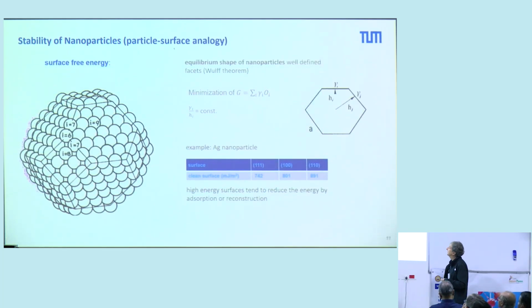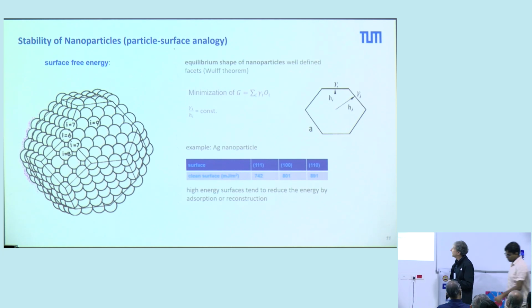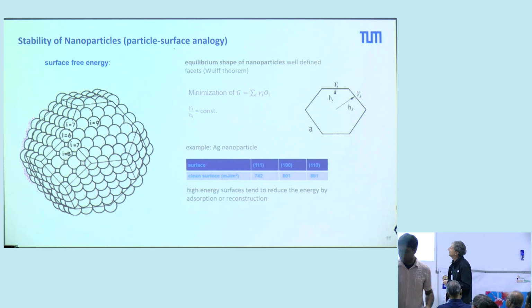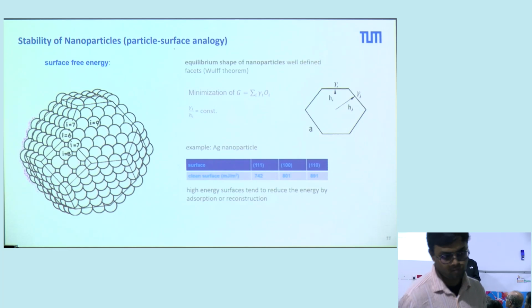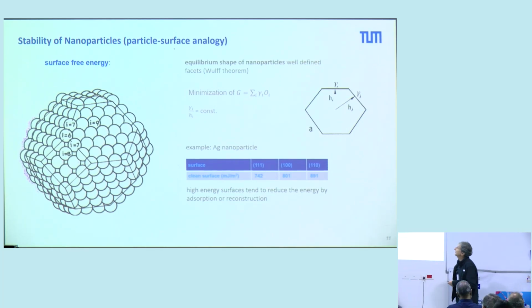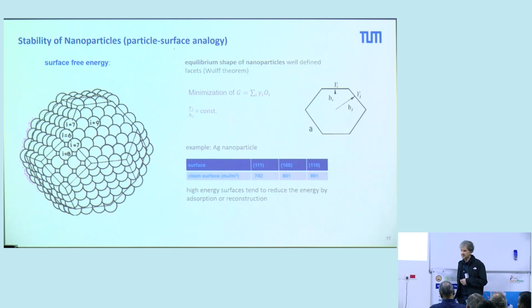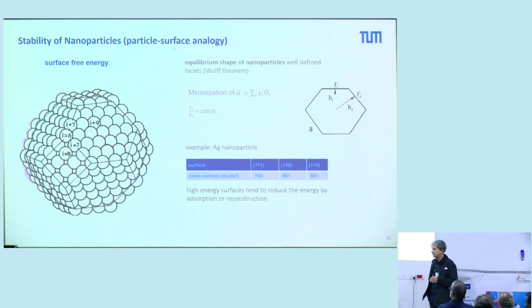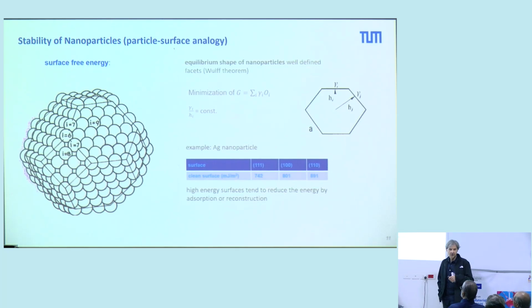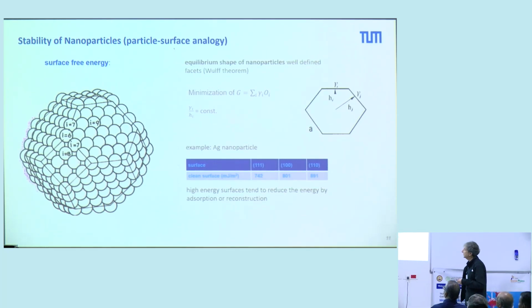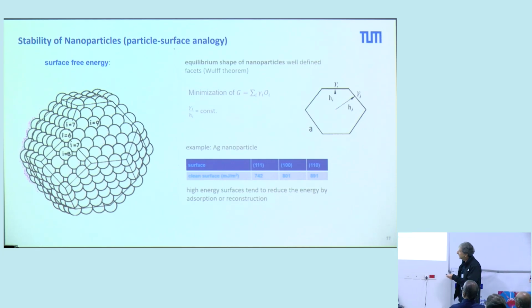It is the Wulff theorem, the Wulff shape. But what is important here is that we have facets which are very similar to single crystals. That means we have a particle surface analogy in this scalable size regime. That means if you learn properties from single crystals, we can apply them to these nanoparticles. Of course, we have a different ratio of these facets. We also have borders of these facets which will be relevant for a catalytic reaction. For instance, if you have a diffusion, you have a hindered diffusion along these rims.